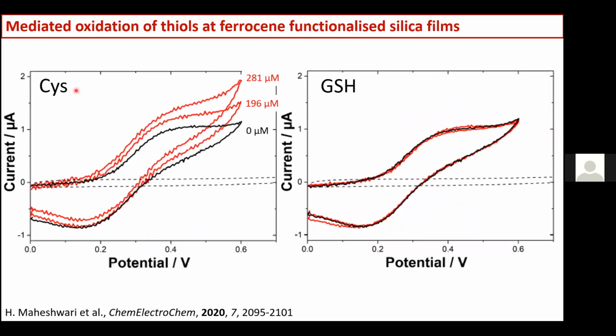So then we did some cyclic voltammetry in the absence of thiols. So this is the line in black here. And then when we added the cysteine, we could see that the signal was slowly increasing on the oxidation side, and then it was slowly decreasing on the reduction side as well. So suggesting that indeed cysteine was being detected at those ferrocene functionalized electrodes. But when we did try with glutathione, we see no significant differences with the CVs with the addition of glutathione.